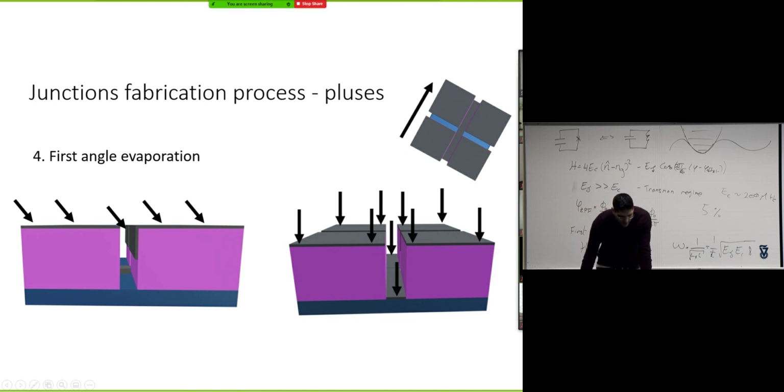these extra layers of evaporation. If you evaporate at an angle over here, what will happen, if you have a high enough aspect ratio, is the metal will go on top. But if you come from this angle, the metal will catch the edge over here of the polymer. But if it's coming from the trench, then it will go into the trench over here. So on the top view, you can see that you get metal along this line, but nothing along this line because the metal caught onto here.